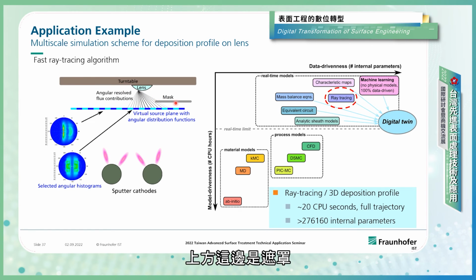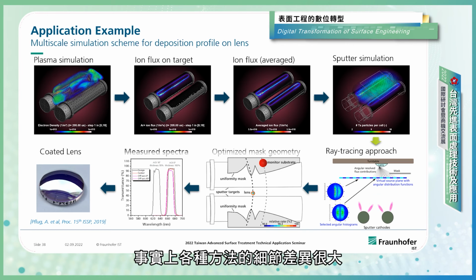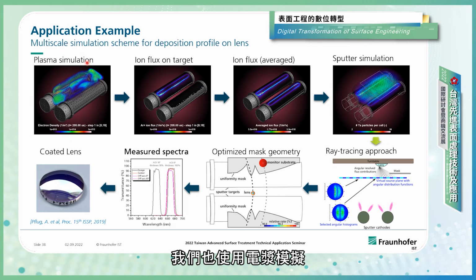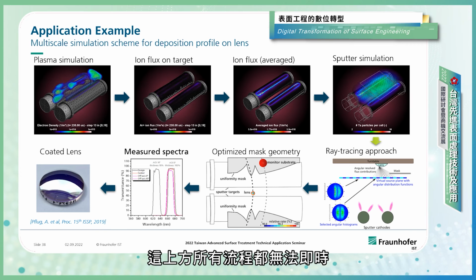There is some masking to homogenize the coating distribution in the situation, and the table is turning all the time. And we provide selected angular histograms in that case for each position and can trace it back. And by that we can calculate the situation for the coating thickness. In detail, it's a lot of different contributions that we see. We use plasma simulation, which we have seen is time consuming, is not real time. So all the processes here on that line are not available in real time, but we use plasma simulation.